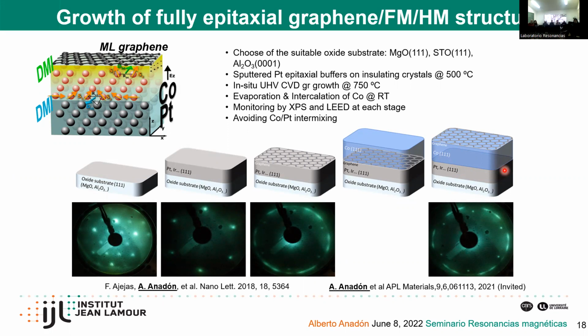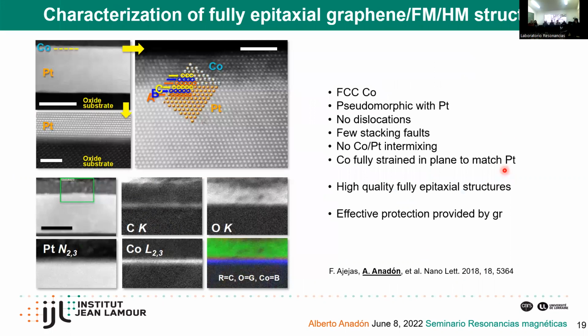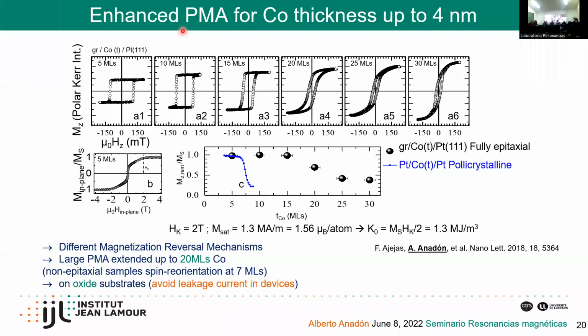In the end, what we find by TEM images is that we have FCC cobalt, which is pseudomorphic with platinum, with very few dislocations or faults, and very small intermixing and so on. So basically, as I said, we have very high quality samples prepared using this method. One of the most interesting things of this type of stack is that the perpendicular magnetic anisotropy of cobalt increases significantly up to 4 nanometers. Normally, the reorientation transition for a platinum-cobalt-platinum system goes between 5 and 10 monolayers of cobalt.